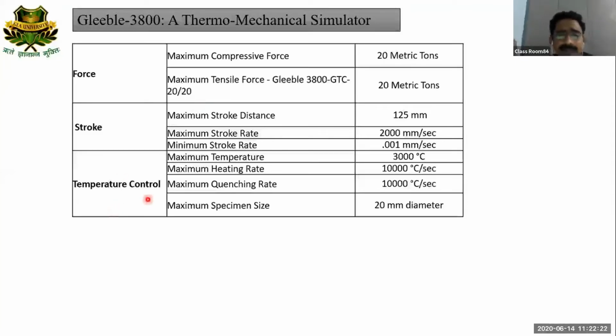So now about the temperature. The maximum temperature it can reach is up to 3000 degrees centigrade, and it has the capacity to raise the temperature by 10,000 degrees in a second. As well as the quenching rate, which we can control, is around 10,000 degrees centigrade per second. The maximum specimen size is 20 mm in diameter. This is the maximum specimen size for all kinds of experiments.